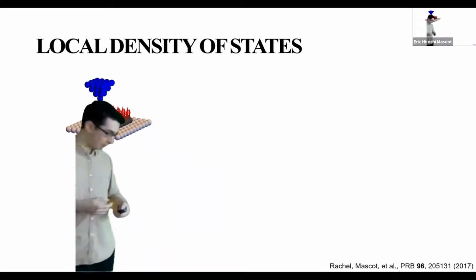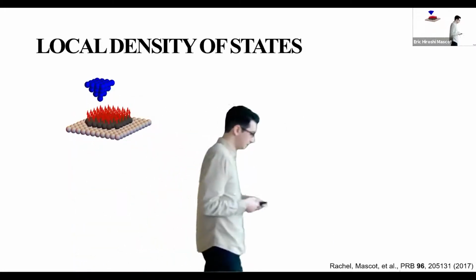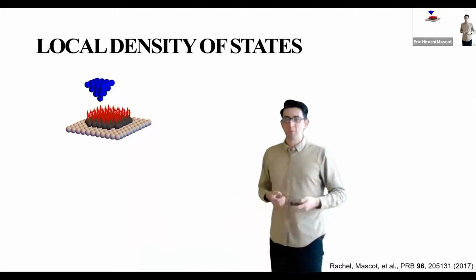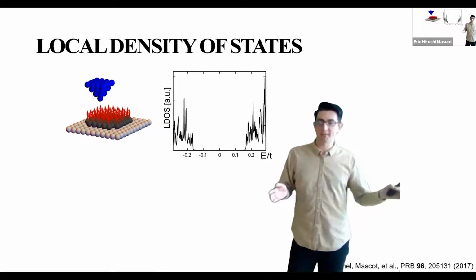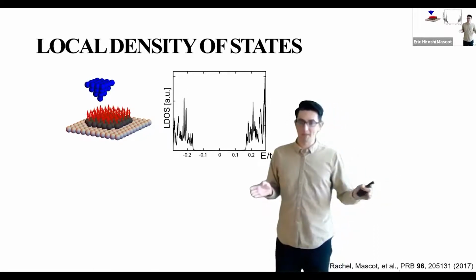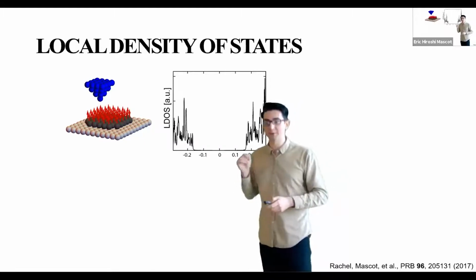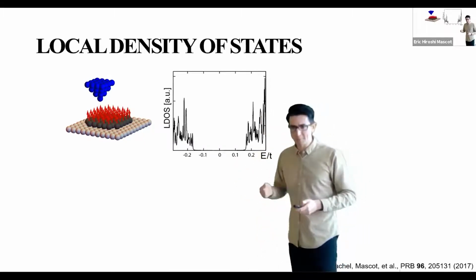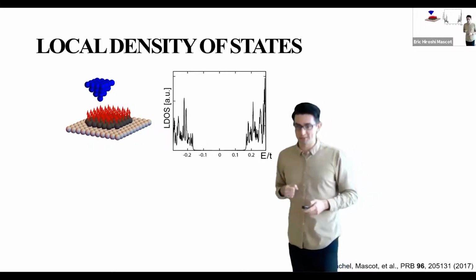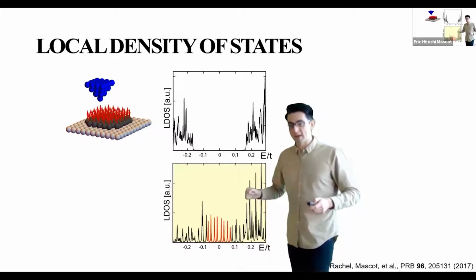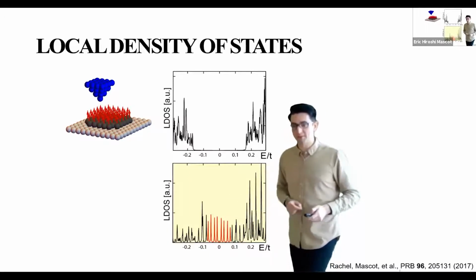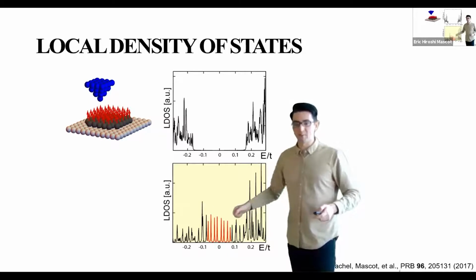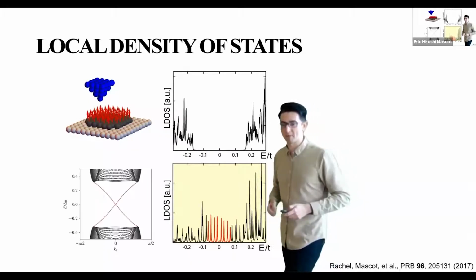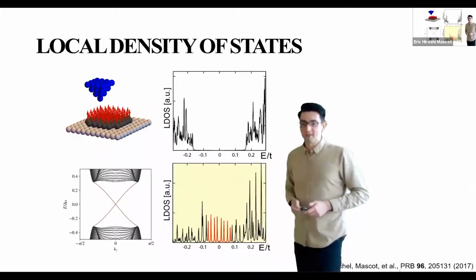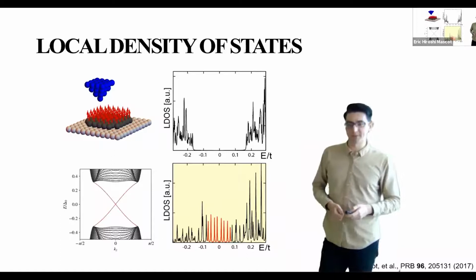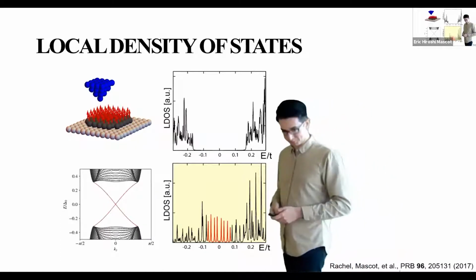And so what should we see in a trivial island of magnetic adatoms? What we should see is just a superconducting gap and no Majorana edge state. So here we see just the superconducting gap, but if we go into a topological phase and measure the LDOS at the edge of this island, then what we expect are these edge states very, very close to zero energy, and they're pretty evenly spaced inside the superconducting gap. And that comes from having a very close to linear dispersion on the edge of the island.